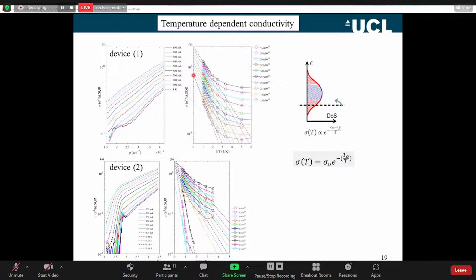You can imagine that as we lower carrier density, the holes have less material to diffuse through. It's still diffusion, the holes have less material to diffuse through, so the high temperature intercept tends to come down because of this percolation effect. It does actually come down to a constant point, and I'll come on to that in a few slides' time. So it's still this thermal excitation to a mobility edge. It's very, very well described by Arrhenius behaviour.